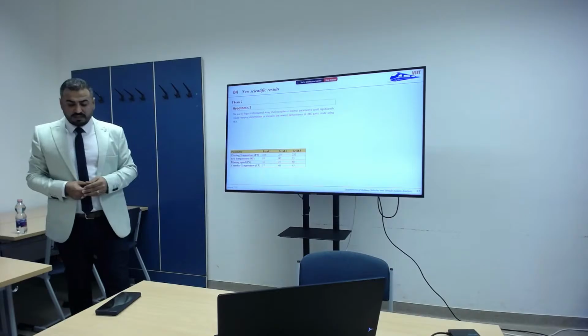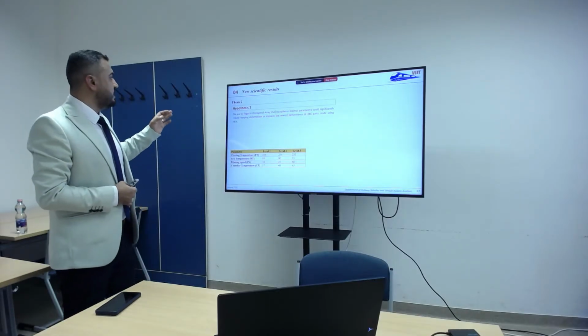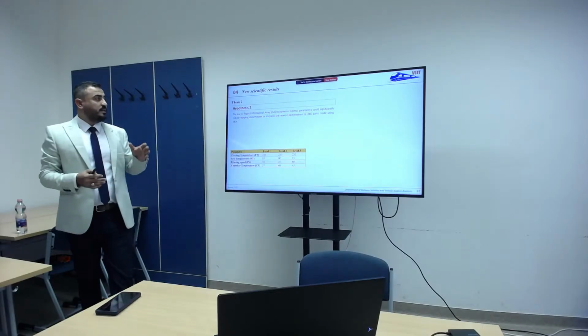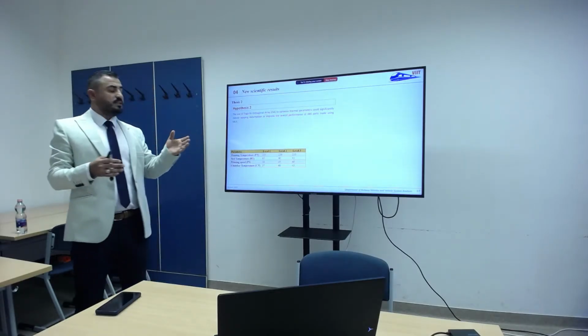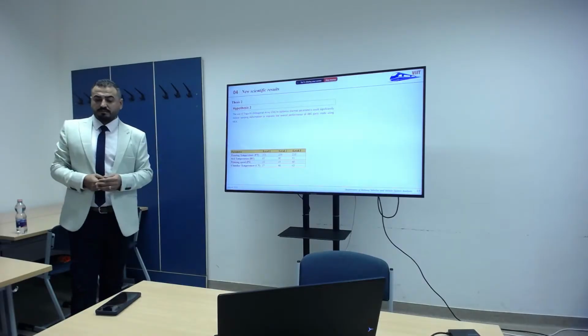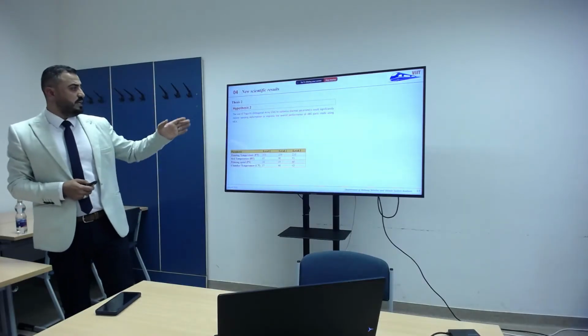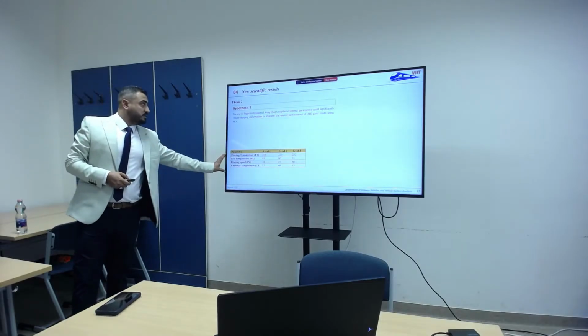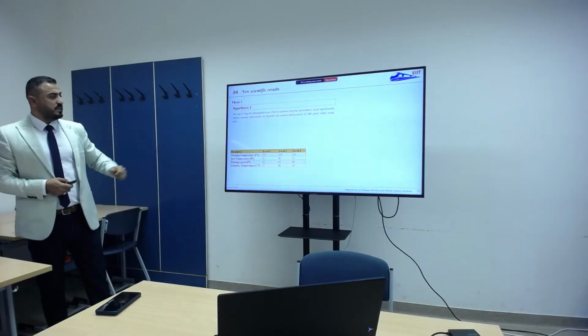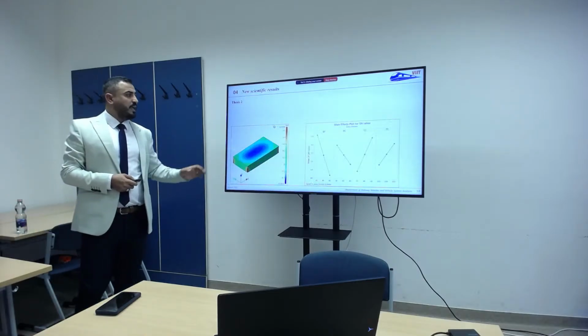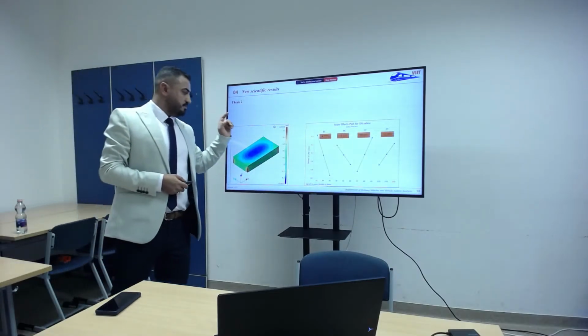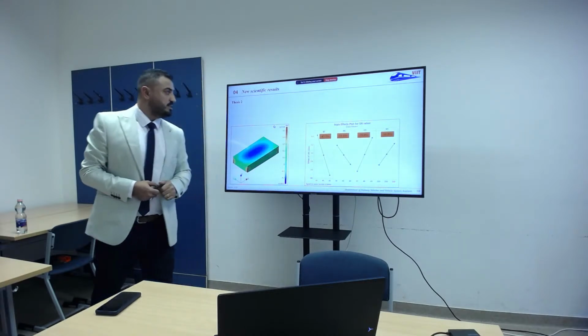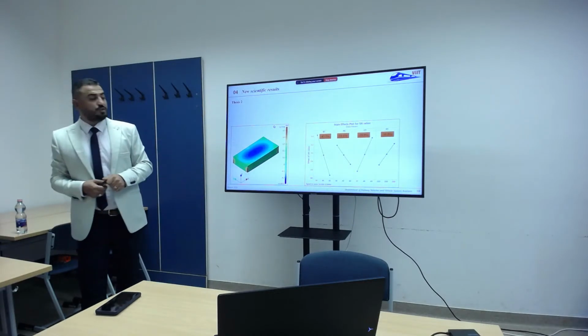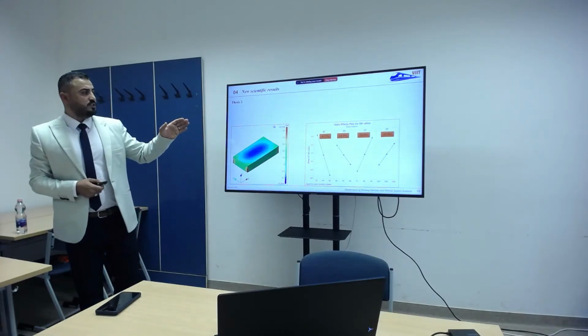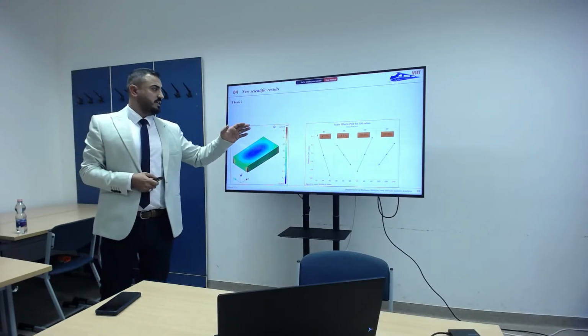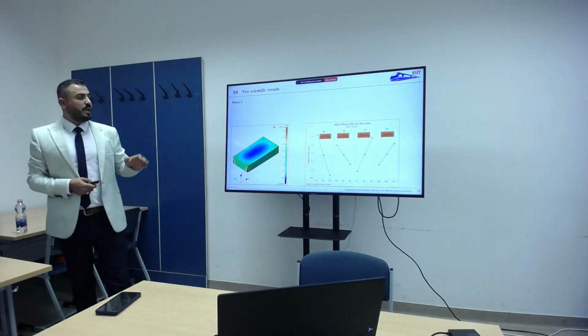For thesis number 2, the proposed hypothesis was that the use of the Taguchi orthogonal array to optimize thermal parameters could significantly reduce the warping deformation in material extrusion 3D printing of ABS parts. In this thesis, I investigated 4 different thermal parameters with 3 levels, and I found that the bed temperature was the most dominant factor with about 47% contribution, and the chamber temperature was the second one with 30%, and printing temperature and printing speed about 11% each.